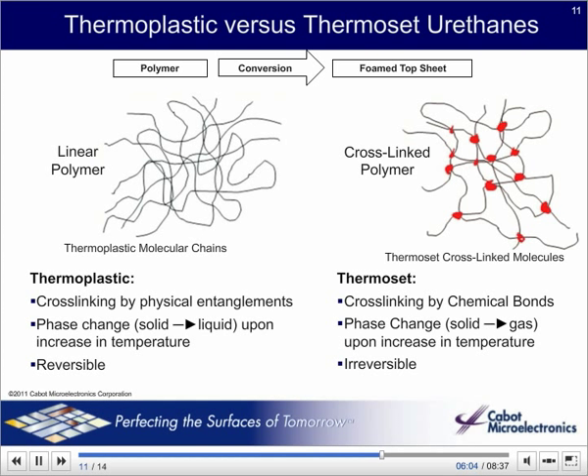Another big difference between Cabot Microelectronics rubber and the rest, we use something called thermoplastic rubber, and all the other guys use thermoset rubber. In thermoplastic, the rubber is made up of long polymer molecules that basically tangle up, and this is reversible. If you heat it, it flows, and if you cool it, it is stable. With thermosets, however, they cure the rubber permanently using chemical bonds. Once you've cured a thermoset, it is permanent. Can anyone guess why this difference can be important? Here are a couple reasons.